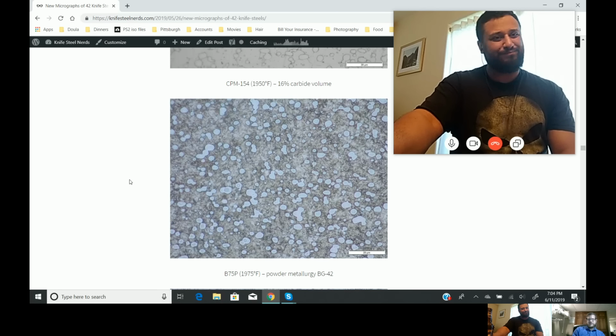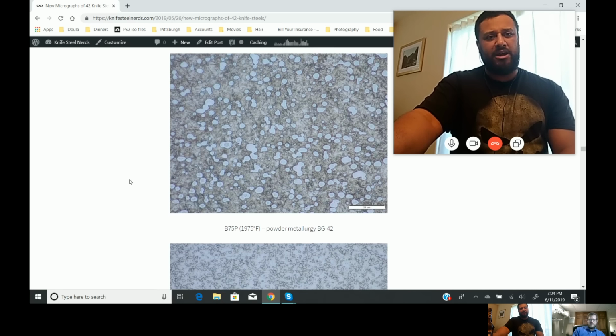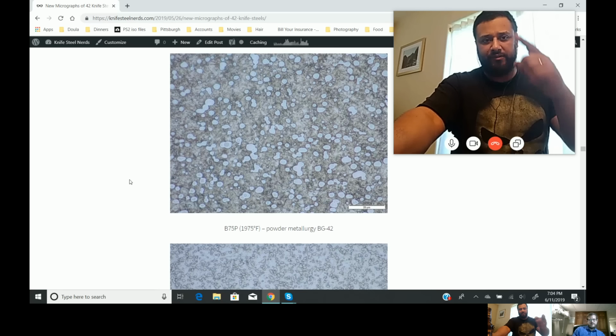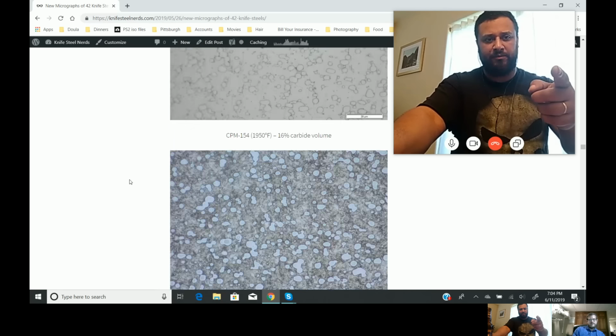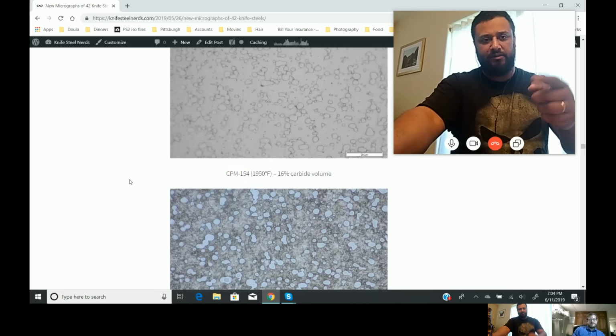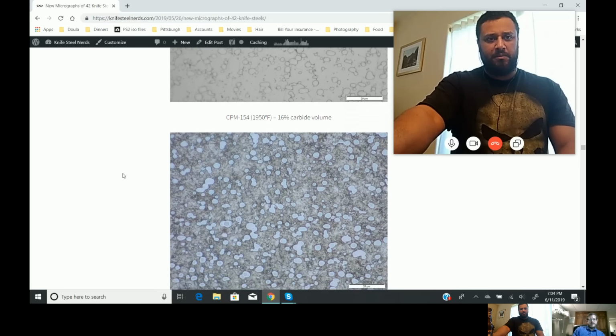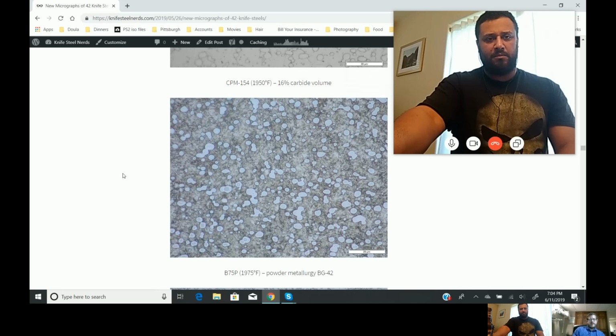B75P, that's Powder Metallurgy BG42, looks very similar to CPM 154, which makes sense because their composition is very similar. Now we have basically the same kind of carbides between these, right? Except we have vanadium enhanced, like an M7C3 carbide, versus up top here with CPM 154. Yeah, so the carbide should be a little harder in the B75P. So it could be that this steel offers a little bit better toughness wear resistance balance. That's a possibility for sure.